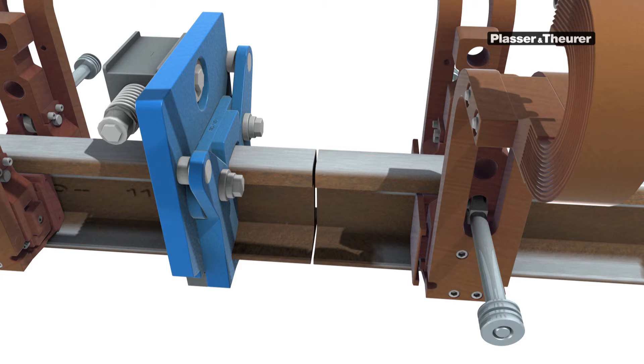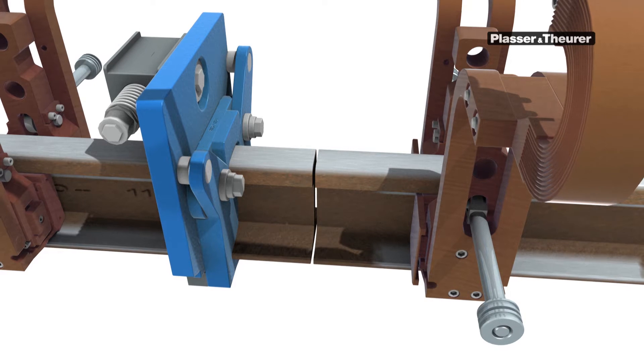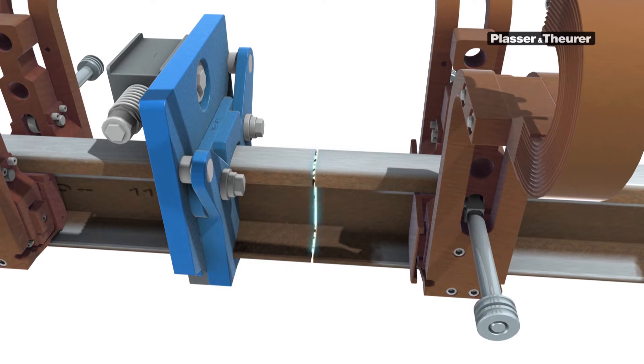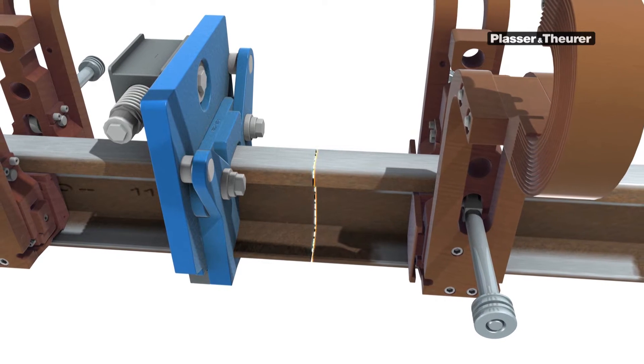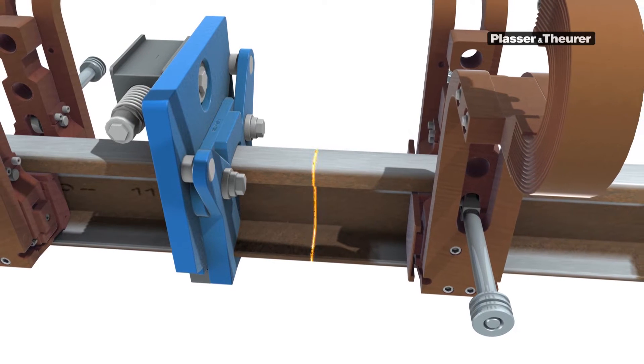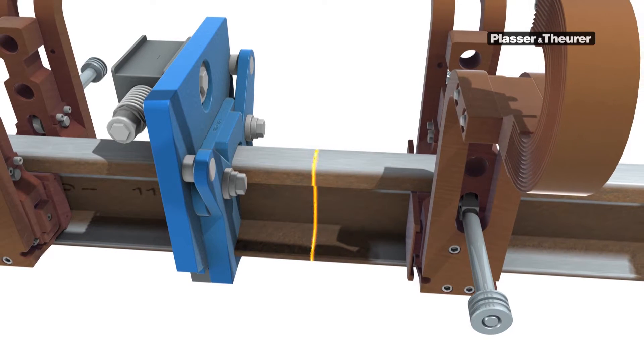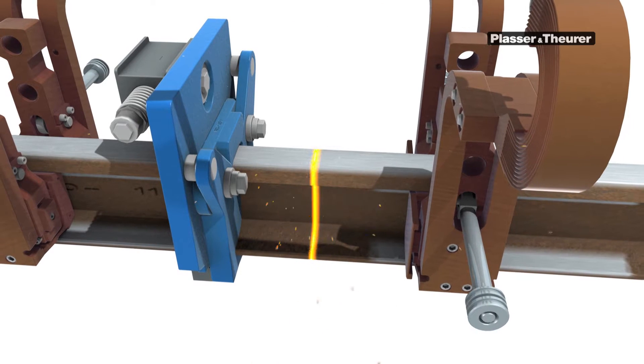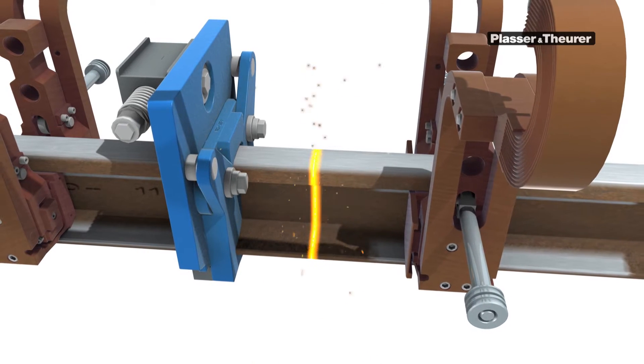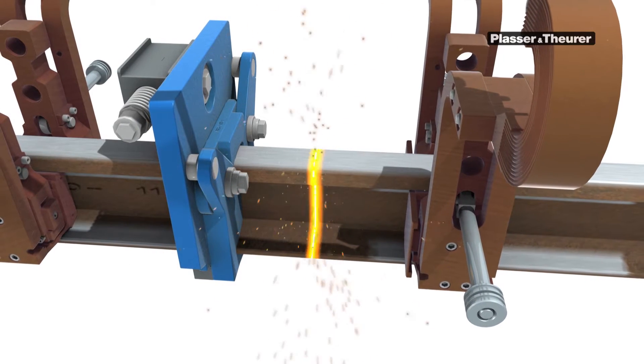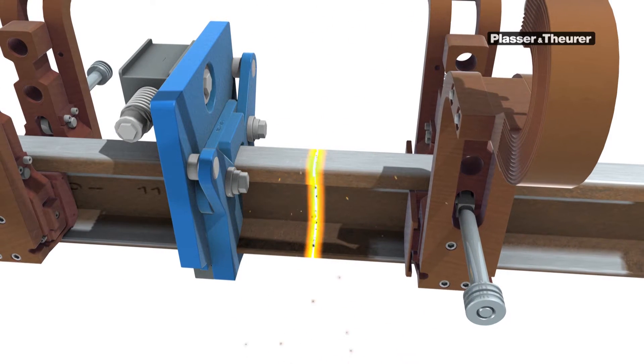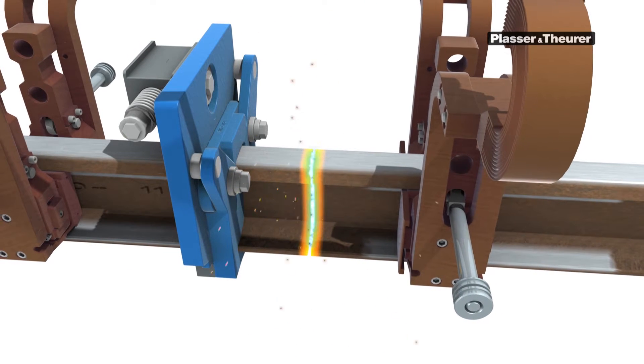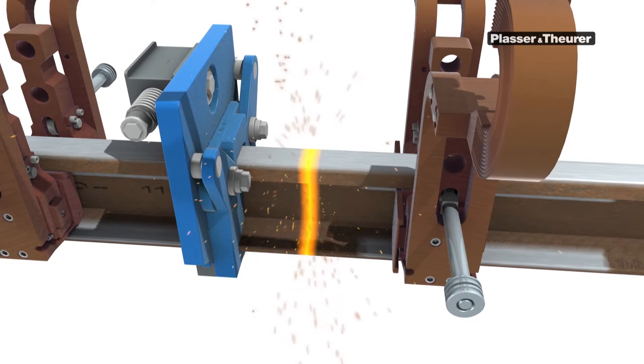Using this method, the two rail ends are heated by the supply of a high electric current, in the form of a regulated direct current short circuit, until melting temperature is reached. This causes a burn-off, which is compensated by automatic guidance of the rail ends.